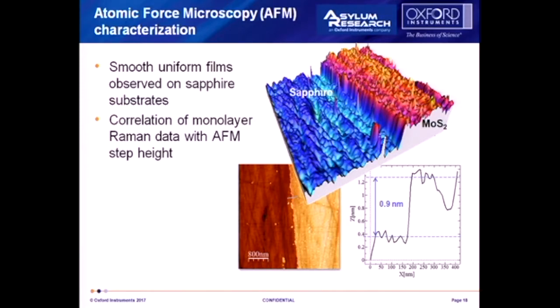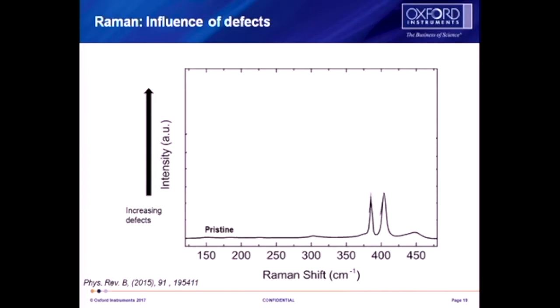Now, one of the biggest problems we had was looking at the quality of the material that we had deposited. With graphene, you can see there's a defect peak, the D peak, which gives a very big D peak. But with the pristine material, we didn't have a way of knowing what was done. But there was a study done with ourselves and the National Physical Laboratory, where they actually deliberately tried to damage the pristine surface to then look at the quality of the material